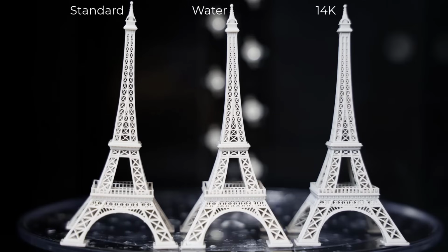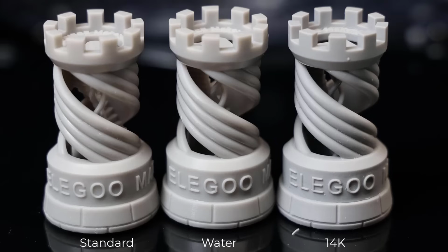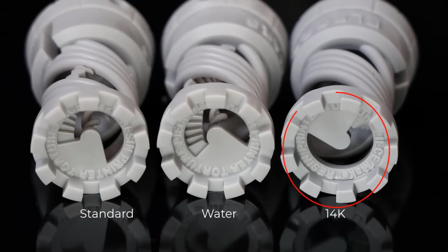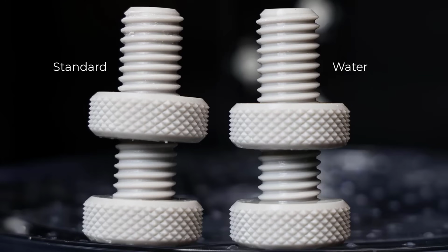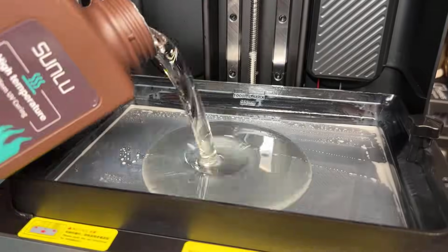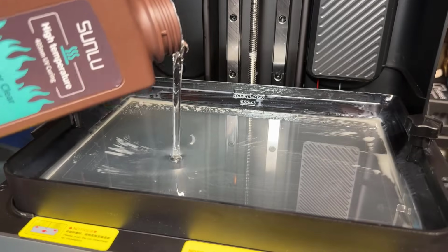For the Eiffel Tower, which lacks small surface details, all three resins look very similar, with no noticeable differences, even under a macro lens. However, for the Elegoo Rook, the difference is more evident. The text is crisper, and the edges are sharper on the 14K resin model. The text on top is also cleaner on the 14K resin model. As for the bolt and nut, since the print with the 14K resin failed, the standard and water washable resins performed identically. Then, I will test the high-temperature resin.